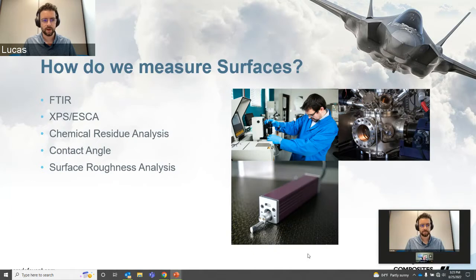But how do we really measure them? Well, traditionally, we've got a couple techniques, right? We've got FTIR. We've got vacuum techniques like XPS, X-ray photoelectron spectroscopy. We can do some chemical residue analysis, through say solvent extraction. We can do wetting methods like contact angles, and we can do surface roughness analysis. Now, a lot of people do roughness post-prep because the common wisdom is we need to roughen surfaces to get good bonding. It tells us nothing about surface chemistry, simply tells us if we hopefully got the surface a little bit rougher. It can be important, usually a secondary effect for bonding, not a primary effect.